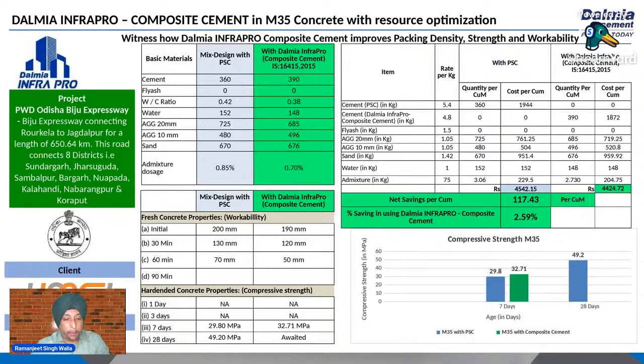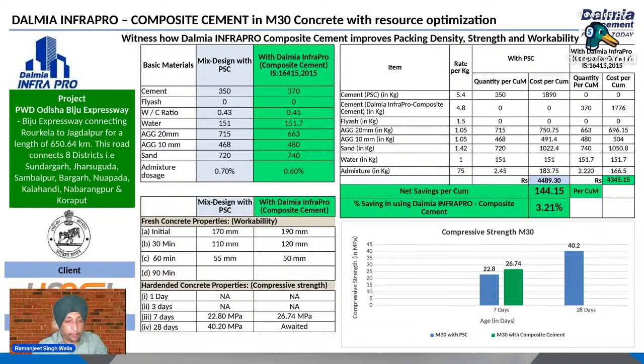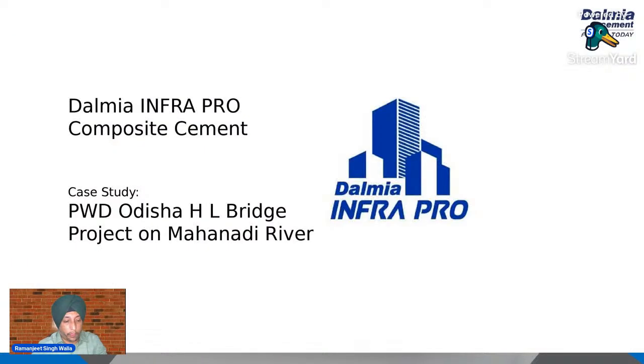This is one more study with our composite cement, M35 grade, in a highway project. Here we use 390 kg of cement, and if you are able to read the slides, the water requirement of these cements is lesser than our OPC cements. That's why we are able to get better strength, and the admixture content which OPC requires is lesser here. So this is M30 and M35, two grades we have done.